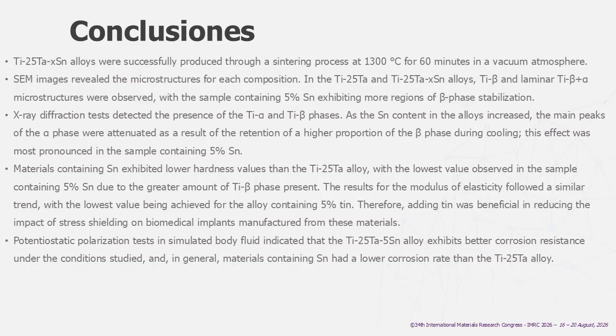And finally, the potentiodynamic polarization test in simulated body fluid indicated that the titanium 25 tantalum 5 tin alloy exhibits better corrosion resistance under the conditions studied, and in general, materials containing tin had a lower corrosion rate than the titanium 25 tantalum alloy.